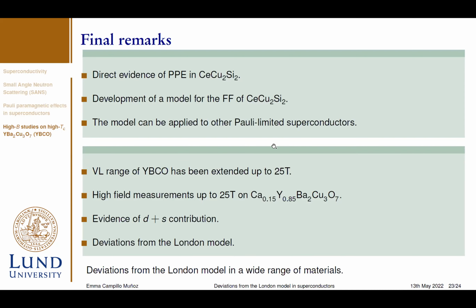Also, we extended the range that the vortex lattice was measured up to 25 Tesla. And we also performed these high field measurements on a 15% calcium doped YBCO sample. And we found evidence that this change in the vortex lattice structure is because of the d plus s wave contribution to the superconducting gap.